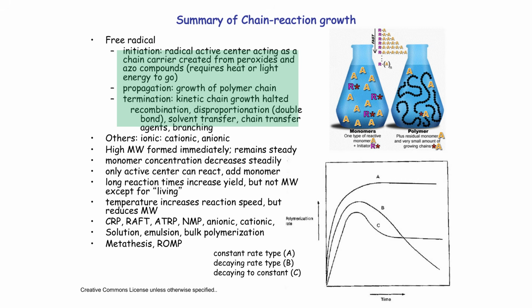The process has 3 distinct phases: initiation, where the active center is formed; propagation, the rapid growth of the polymer chain; and termination, where the growth is halted, for example by 2 radicals combining. High molecular weight polymer is formed almost immediately, and it remains steady throughout the reaction. As the reaction proceeds, the monomer concentration steadily decreases. Longer reaction times increase the yield of the polymer, but not necessarily its molecular weight, unless it's a special type of living polymerization, where termination is absent.